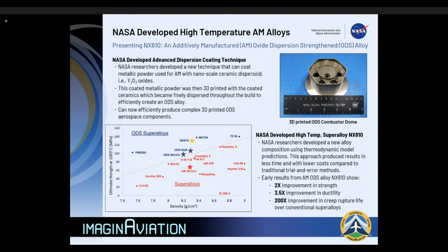And in our initial tests, one, we were able to print it, and we were able to show the microstructure that was predicted by the model. And so that was right off the bat a really encouraging result, and helped support that some of these thermodynamic models are becoming robust enough to help us actually design new alloys moving forward. But then we started to actually test the high temperature properties of this new alloy NX810. And if you can see here again on this graph, NX810 is this yellow curve or yellow star.